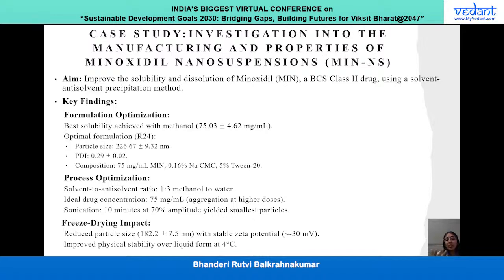Particle size was, as you can see, 226.67 plus or minus 9.32 nm. PDI is shown: 0.29 plus or minus 0.02. Composition: they have taken 75 mg per ml minoxidil and 0.16% sodium CMC, 5% Tween 20.